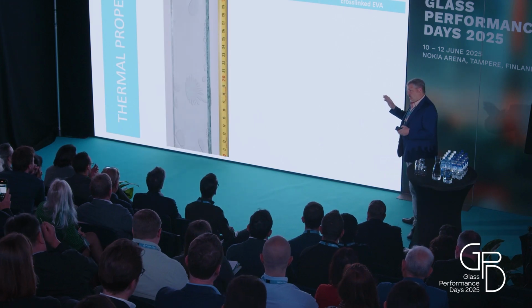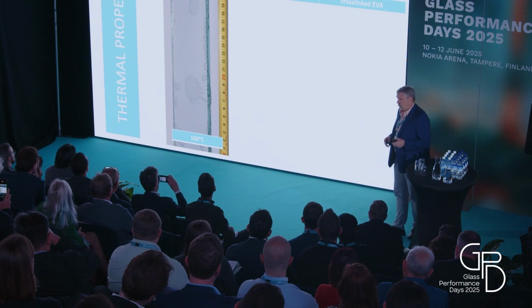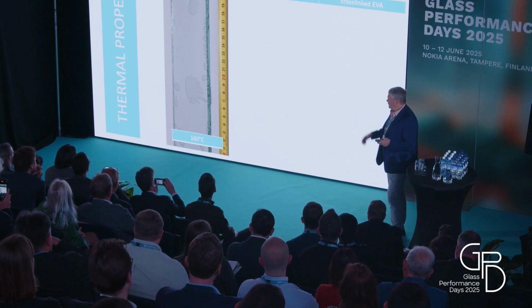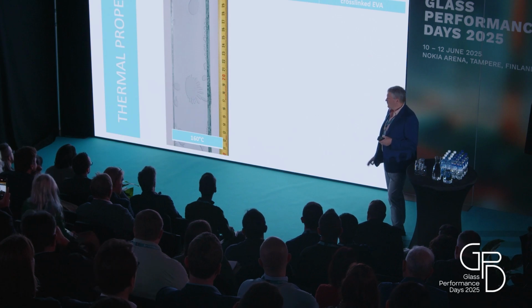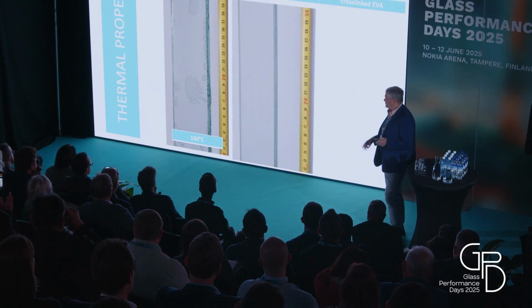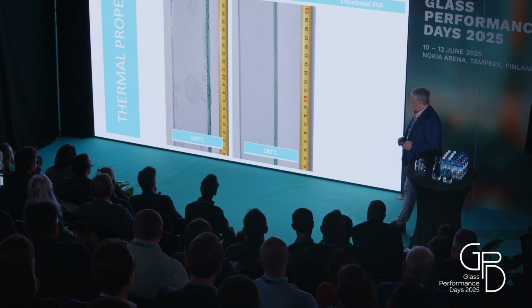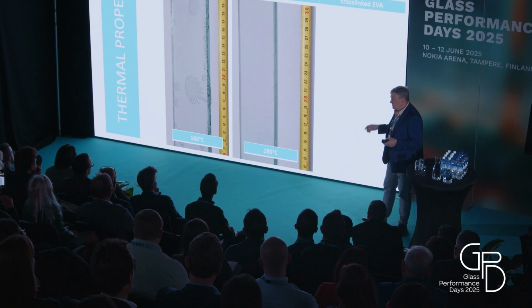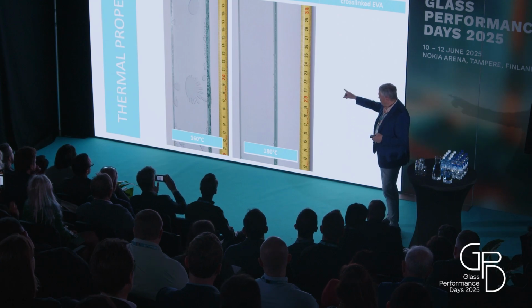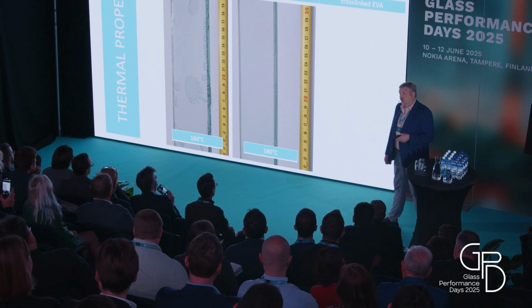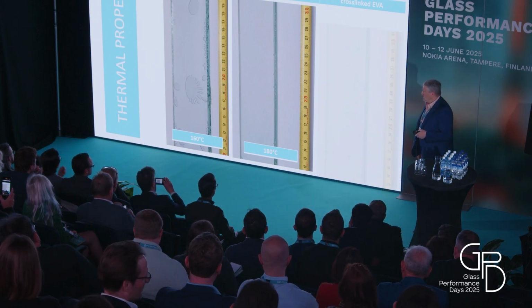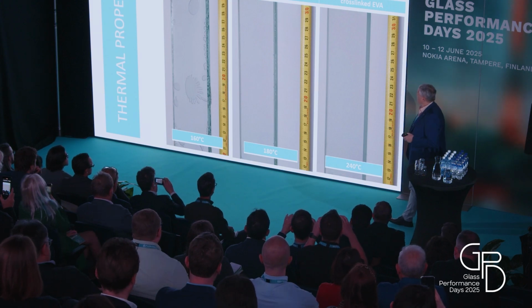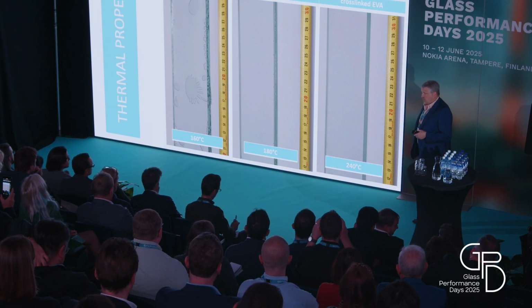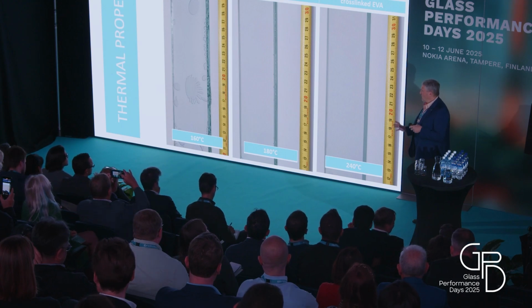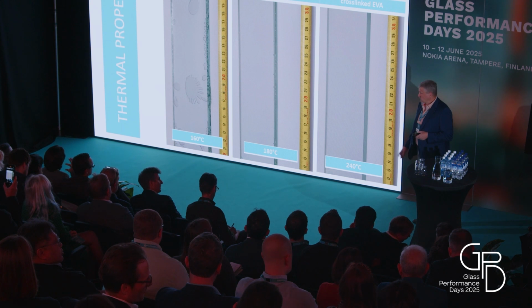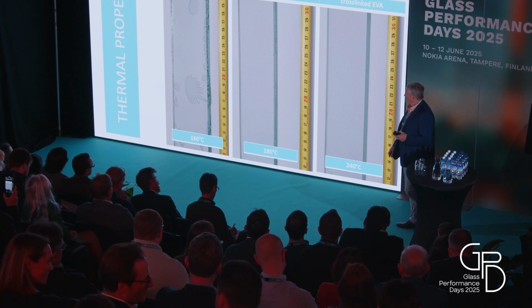As we have seen already in the former presentation, this is well known that PVB has a problem at higher temperature. When you achieve temperatures above 150 degrees C for a certain time, then you will find effects like this. You see kind of bubbles in this laminated safety glass. Thermoplastic ionomer, like Sentry glass, well, it's better, but you see on the edges that the formation of bubbles also starts at temperature of around about 180 degrees C. Compared to this, we have done this test with an EVA cross-linked interlayer, and up to 240 degrees C, when this test was over, we have not seen any failure on this. And you can see also from the edges, no yellowing or something like this.